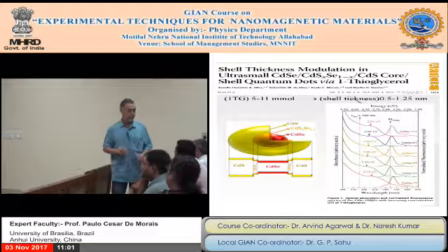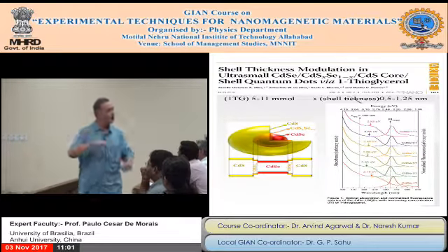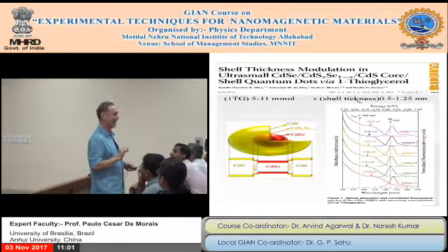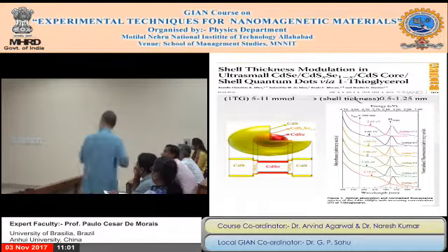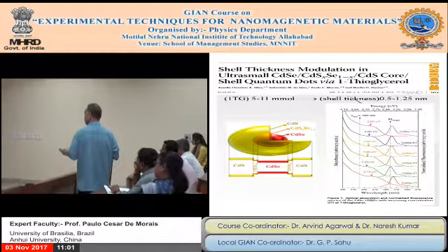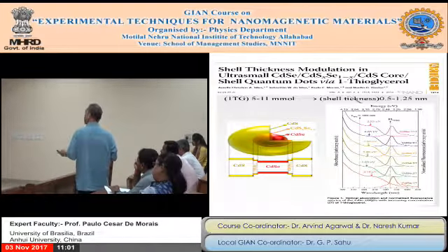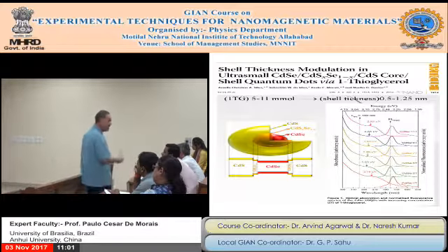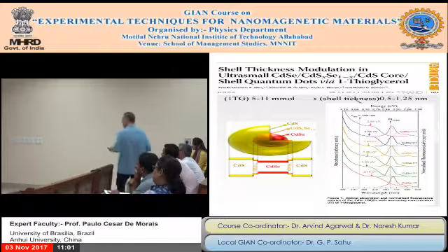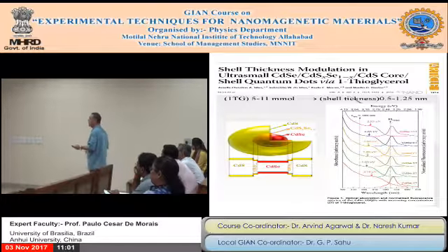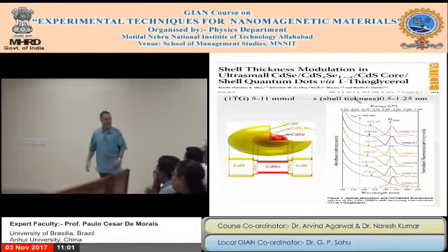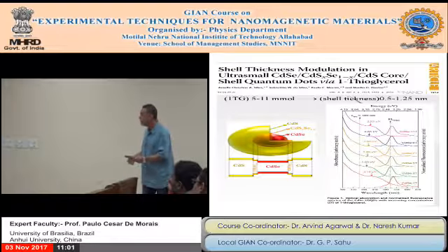Cadmium sulfide. But in between the two, there is a transition region. It's an alloy, actually. So the core is pure cadmium selenide. The shell is pure cadmium sulfide. But in between, they mix together. We were able to track this. And then a very important point here were the PL and absorption spectrum. So the way we synthesize this material, and then you can see the gap.